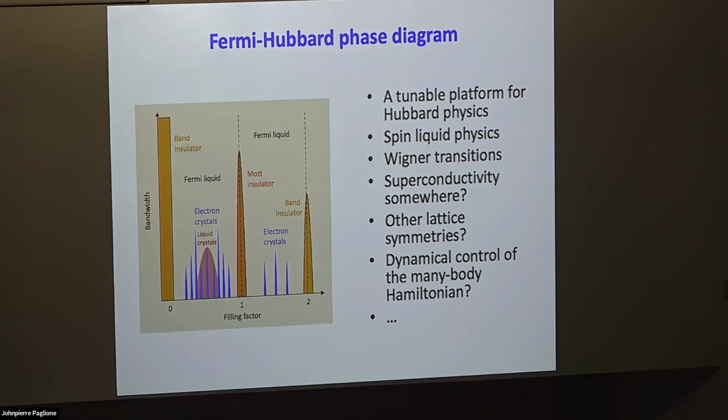My second question is, how do you experimentally detect these states? There are different ways. You can measure transport. They are insulators because the charges are locked to the lattice, so in the small bias limit they cannot carry current. And you can measure the compressibility of the system. These states are incompressible, and when you dope a little bit away, they become compressible again.